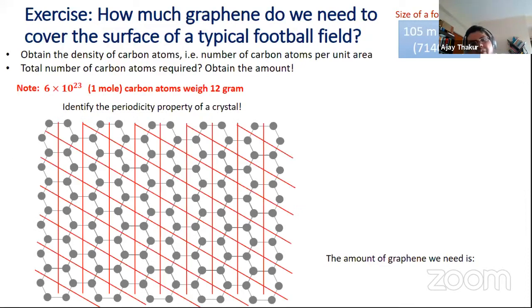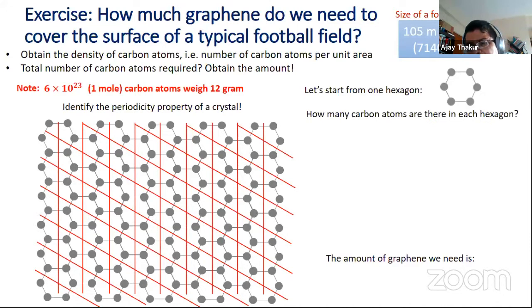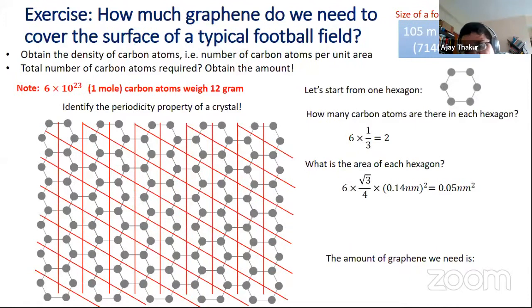Now we can divide this into unit cells. If we look at a single hexagon, each of the atoms on this hexagon is shared by 3 hexagons. So overall, per hexagon, there are going to be 6 × 1/3, which is about 2 atoms. And if a is the separation between 2 carbon atoms, the area of this hexagon is going to be about 6 × √3/4 × the carbon-carbon distance squared, and the carbon-carbon distance is about 0.14 nanometer. Therefore, the area of a hexagon is roughly about 0.05 nanometer squared.